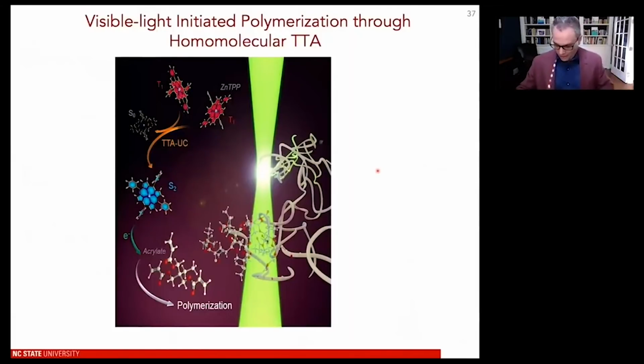To finish on a last topic, I wanted to just do some chemistry now. So you can actually use visible light initiated polymerization by using, now instead of heteromolecular triplet-triplet annihilation, homomolecular, which means that the triplet excited state of the porphyrin will annihilate to produce, interestingly enough, the ground state porphyrin and then the upper S2 excited state of the porphyrin. The S2 excited state will then engage in excited state electron transfer, in our particular case, with an acrylate solvent. And then that actually promotes the free radical polymerization.